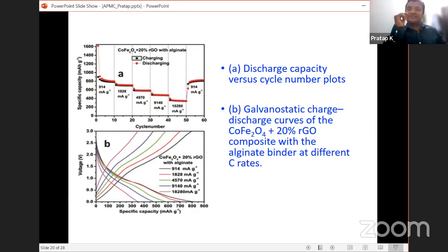So in that way, there are several current rating chargings. What we did was, we tried to charge our material with 0.1 amperes. Then the capacity is around 900. We doubled the current. When we doubled the current, the capacity decreased to around 700.